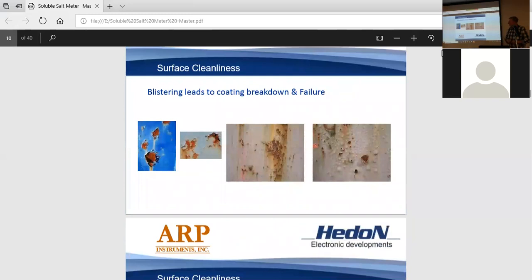And that's what it looks like. A bunch of blistering, corrosion, and undercutting under here. In a ballast tank or an underwater hull, you would have anodes or an impressed current cathodic protection system, either one. It will protect the areas here, but cathodic protection can't go in underneath the coating system, so it won't help you there. But it provides some protection. And that's mainly if it's a ballast tank, if it's in immersion.